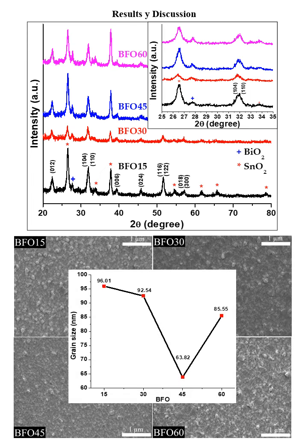The same images show a tendency of grain size to decrease from samples of BFO 15 all the way to BFO 45. In these samples, a tendency of grain decrease is observed. However, for BFO 60, that is the sample of BFO with 60 minutes of sintering time, an increase of grain size is observed.